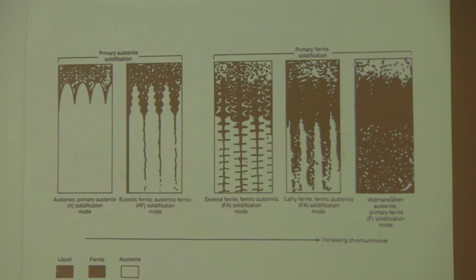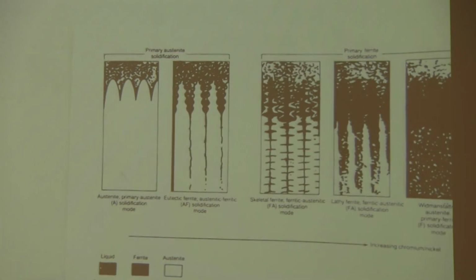If you're a little bit further over on the phase diagram, as you solidify austenite along the boundaries of those solidification dendrites, is what these are called, you do get a little bit of formation of ferrite, and that's called the AF solidification mode. And then these two here are the FA type solidification modes, where you're actually solidifying as ferrite, but then as it cools, you're getting a transformation back to austenite, and what it leaves is this little lathy or skeletal structure of ferrite, basically at the cores of those dendrites. Something that you don't see very often in stainless steels actually is complete ferrite solidification, or F-type solidification mode.